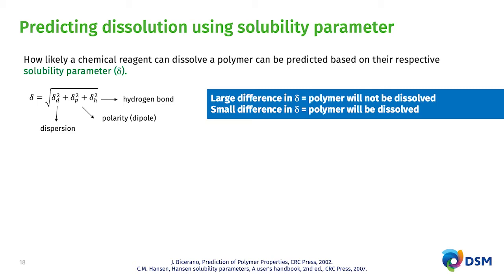To make it a bit more tangible, when you calculate the delta parameters of polymer versus solvent, if the delta parameters of these two are alike or very similar, then it is most likely that the solvent will be able to dissolve the polymer. If the solubility parameters of the polymer and solvent are not the same, then they are likely not to be dissolved.